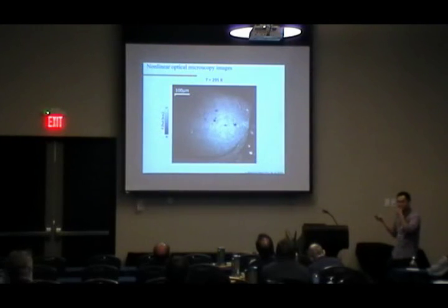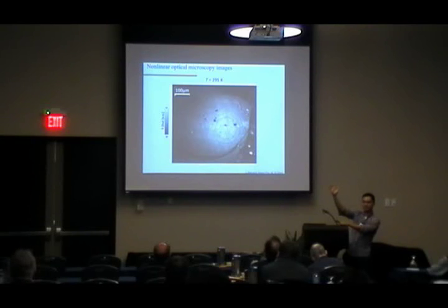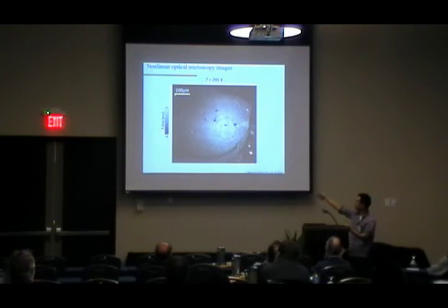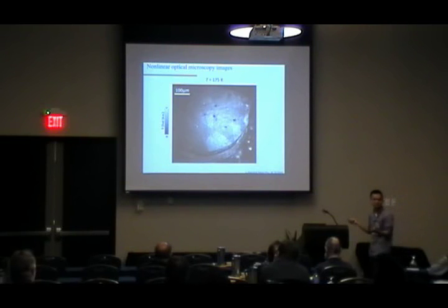So to overcome that domain issue, we did a second harmonic imaging study. Basically what we do is fix our scattering plane angle at some value, and we take a far field image of our sample at that angle. So this is high temperature, what the crystal looks like. It looks pretty uniformly illuminated. There's some Gaussian beam profile that makes the spot brighter here, but that's not intrinsic to the sample. And as you cool it down, you see this patchwork start to develop.